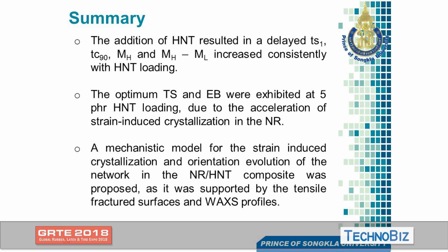Yes, our concluding remarks. As you can see before, the scorch time and cure time are longer once we include the HNTs. Maximum torque and torque difference increasing are typical findings because we include rigid fillers. That means we reduce the fraction of the rubber, making the maximum torque and torque difference increase. Tensile strength and elongation at break are best at 5 PHR.